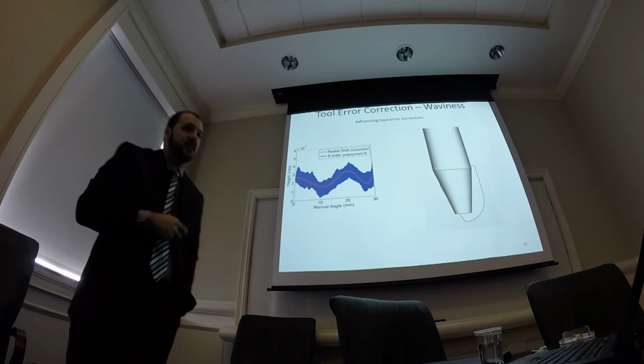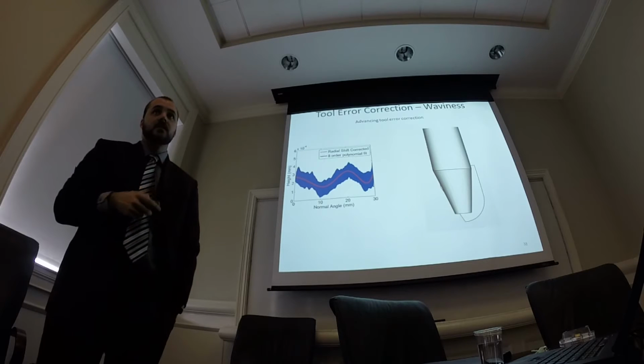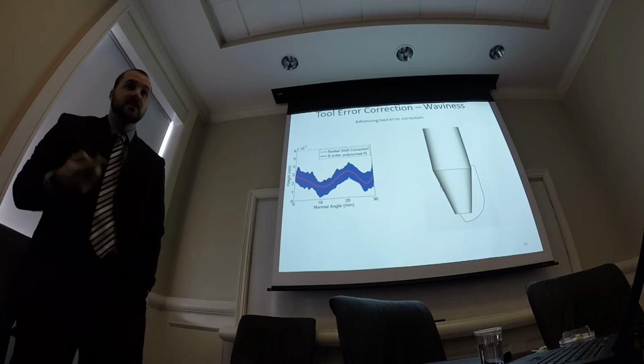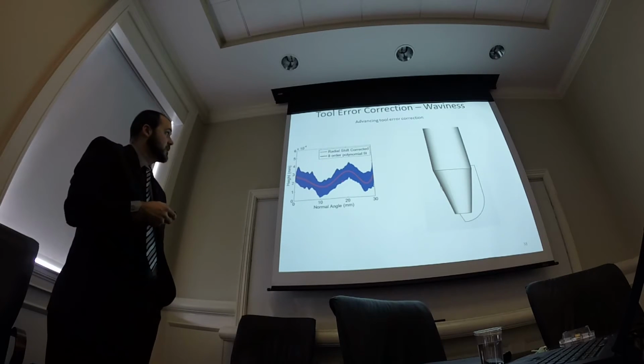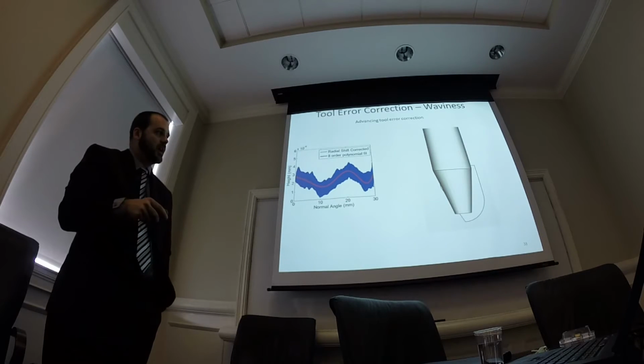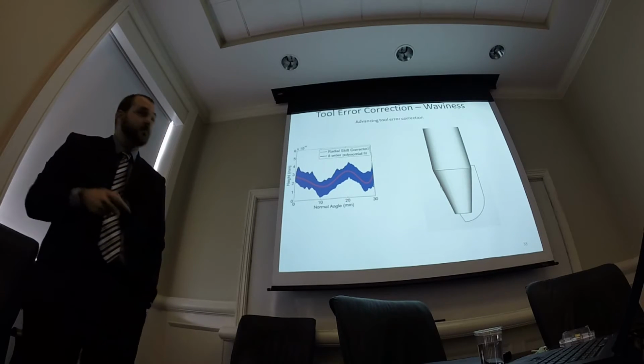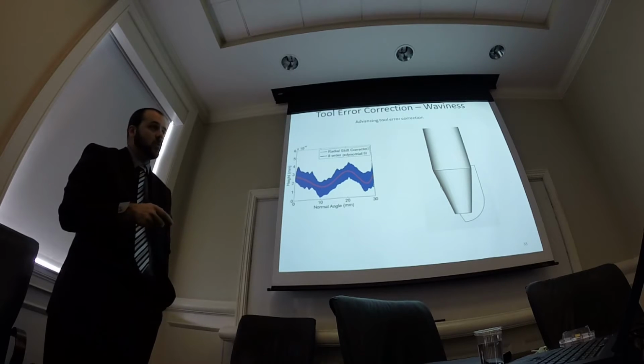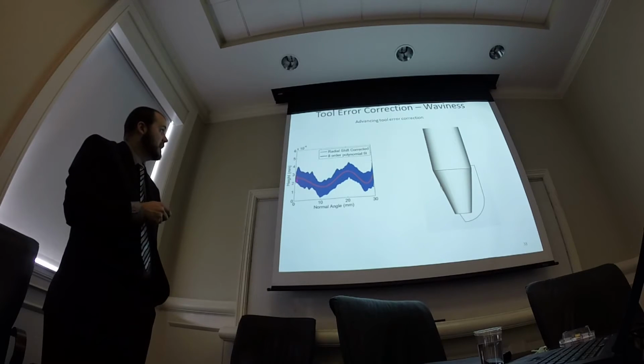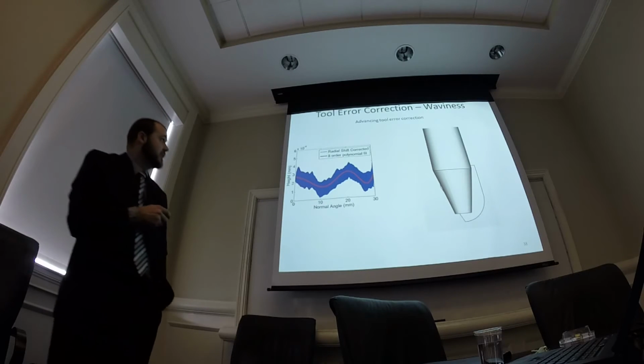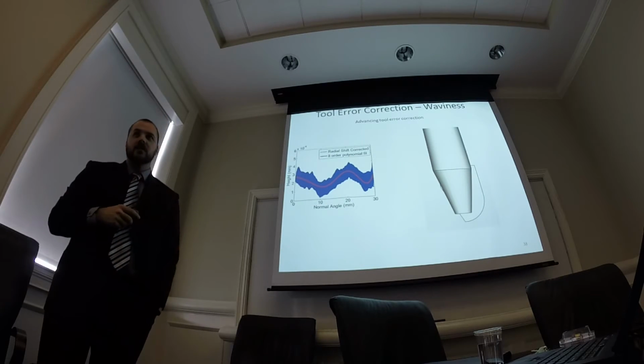All right, so now what's left over is waviness. We've removed our tool error position, our radial shift, and this is what's left. So what I did is I plotted the normal angle that we're seeing on the surface, which corresponds to the normal angle on our tool where it would have been cut, and I'm plotting the height error that we're seeing. And then for this one I used an 8th order polynomial.